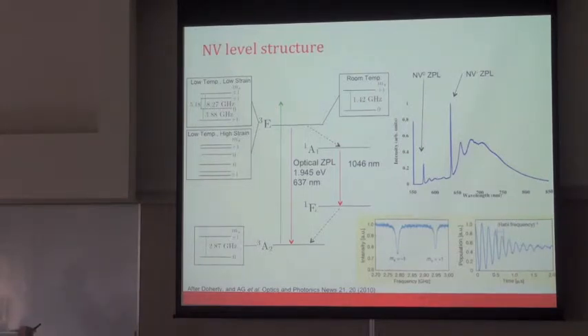The structure, as far as we know, is unique amongst color centers in diamond and is one of only very few color centers in any solid state host that shows its properties. It has a triplet ground state here, and the transitions from the ground state to the excited state are approximately spin conserving. So you can excite up here to this excited manifold with a green laser off resonance, and then you will see emission here in the red. The lifetime of this excited state varies depending upon the exact form of diamond you're in, but as a rule of thumb in single crystal diamond, it's about 12 nanoseconds.